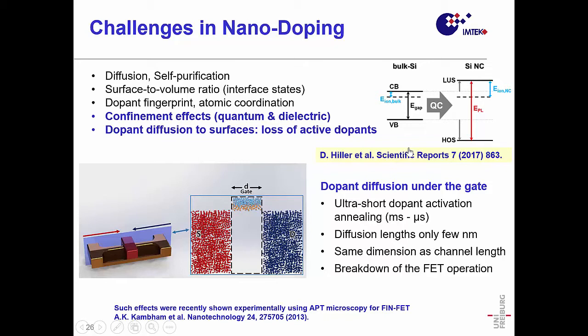On the left-hand side, you see a sketch. If you do a doping inside of a bulk structure, then your doping level is near the conduction band. If you now change by quantum confinement, if you change the size of the structure, you are increasing the band gap. But the level of your dopant is the same. That means the ionization energy you need for that is actually increasing. That's one of the things.